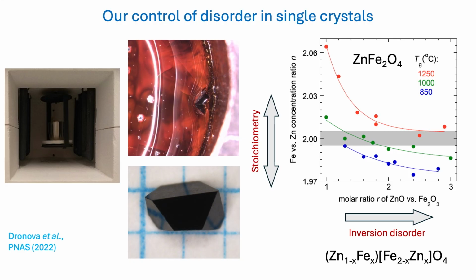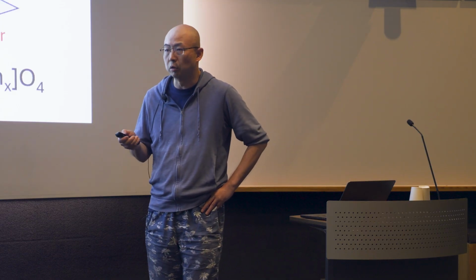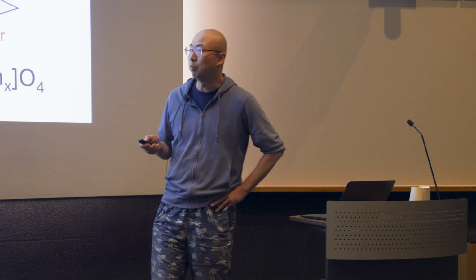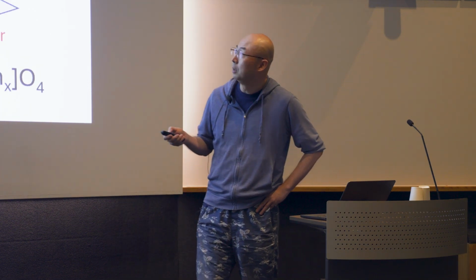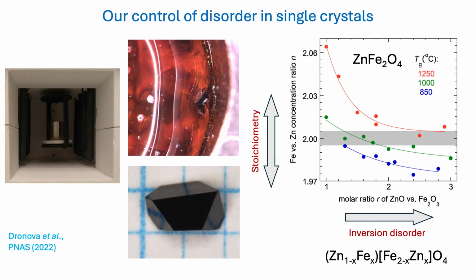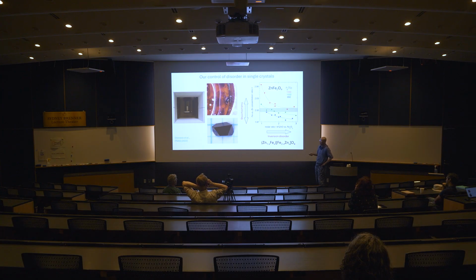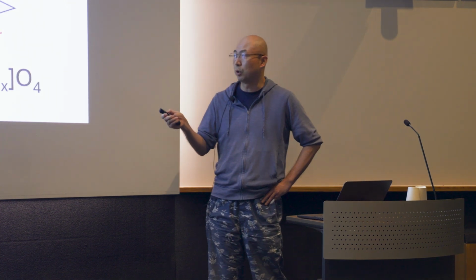What we did differently is that, because of this solution environment, we can actually control what we put in there. Unlike floating zone growth, where you have to have the precise composition because you cannot easily have a solution, here we put into this solution different amounts of zinc and iron oxide, and then we measure the product in the crystal, how much iron and zinc are there. You can see, not surprisingly, they have a correlation, because the more zinc you put in there, of course, the more zinc you have in the final crystal. But nevertheless, you follow a monotonic behavior with what you put in.